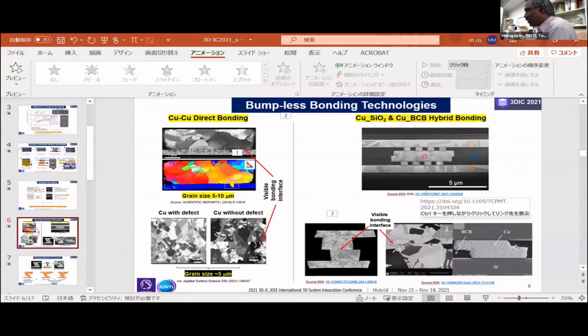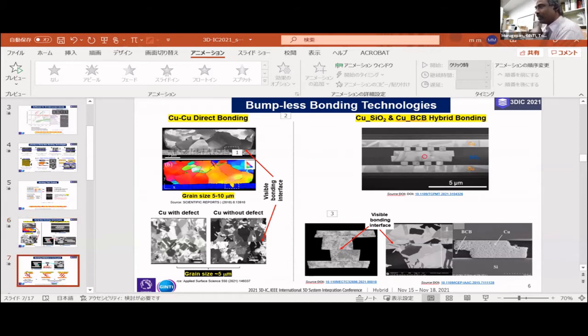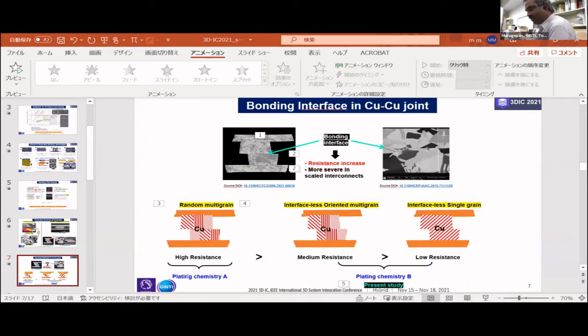It's very difficult. Even if you go for hybrid bonding, it's the same issue. You always see some seam, that is, your top and bottom copper grains never move into each other. Even though here you see some, this is again grain growth from the top one alone. So far, with typical plating chemistry, which is quite common nowadays, whatever your copper film, copper pad or copper bump is before bonding, it is always randomly oriented multi-grain. Rarely some of your grains may match, but obviously it doesn't match your top and bottom grains.